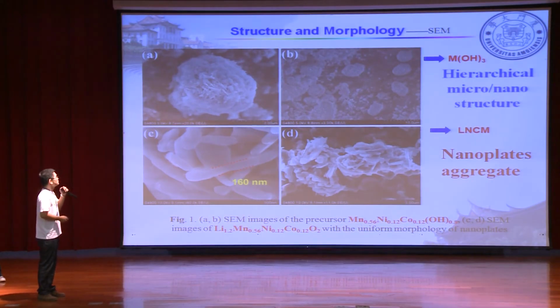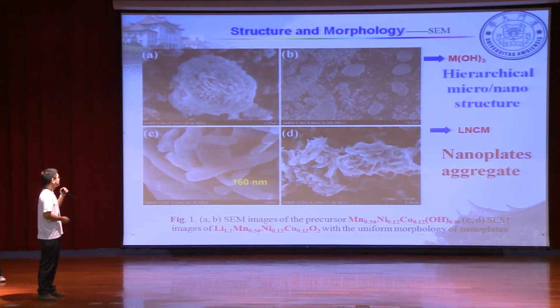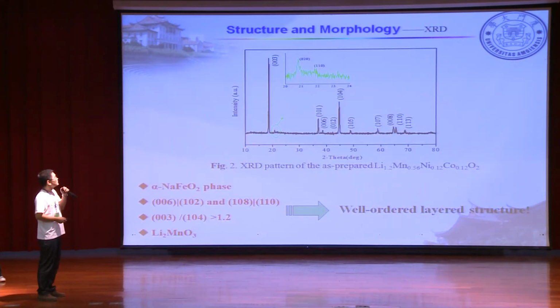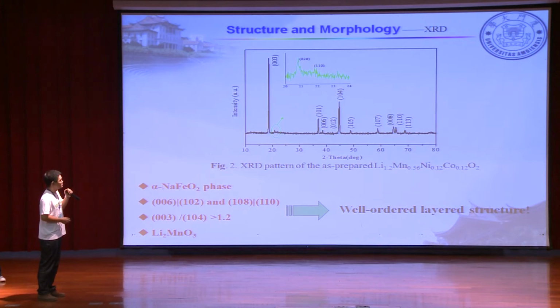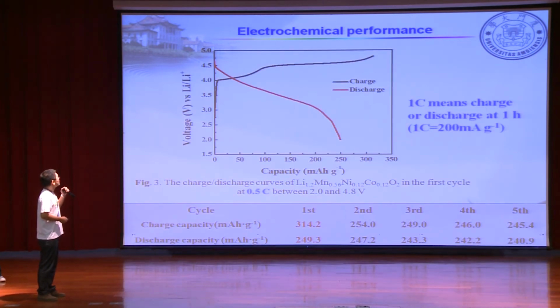Then we use the scanning electron microscopy to characterize the morphology of our products. And the SEM images suggest that the precursor were sphere-like aggregates, and the aggregates mainly consist of thin nanoplates. And more interestingly, the hexagonal nanoplates were retained in the product, except the thickness of the nanoplates is greatly increased, about 160 nanometers. Then we use the X-ray diffraction to test the crystal property, and the XRD pattern suggests that the LNCM has a well-ordered layer structure.